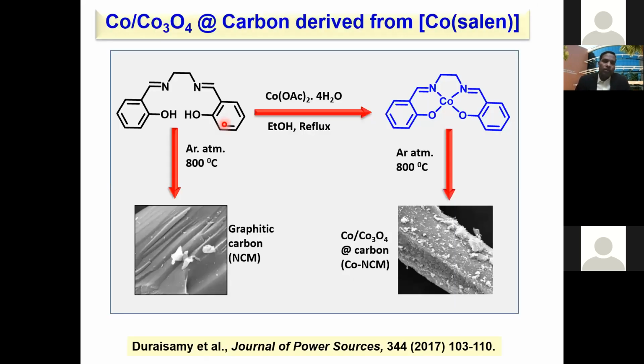The first system is cobalt oxide. This can be synthesized by using a salen ligand. By means of condensation of salicylaldehyde and ethylenediamine, you can get this salen ligand. That is complexed with cobalt acetate. You get a very stable metal complex, that is the cobalt salen complex. Then you get that solid powder and pyrolyze it, decompose it under inert condition at 800 degrees, and you get metal oxide embedded directly on the carbon matrix.